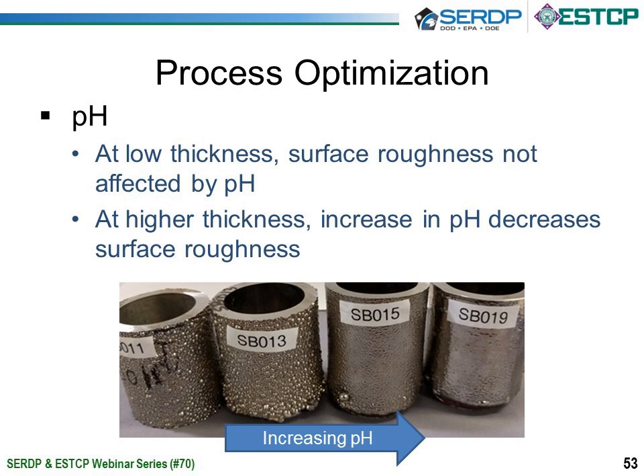In terms of process optimization, I'm not going to go into huge detail regarding the 3 process parameters. Integran did a large amount of empirical evaluation looking at each of these parameters, both individually and in conjunction with one another. In terms of pH, it was found that at low deposition thicknesses, the outer surface roughness really was somewhat independent of the typical pHs employed in these baths.